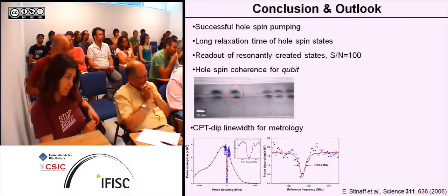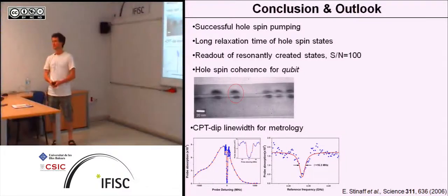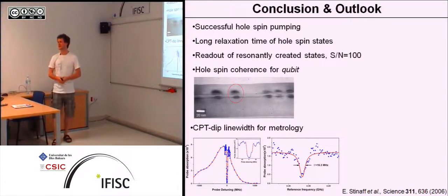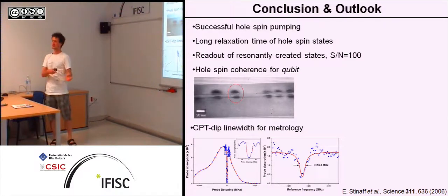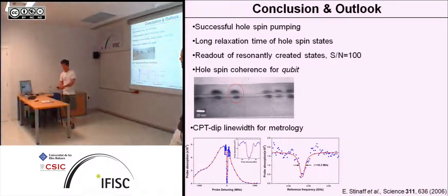Yes. So if I should be completely honest, I don't think you will ever do a quantum computer with this. No way. The different quantum dots are so dispersed in energy, it's never going to happen. But there are different schemes to create this. This is only self-assembled quantum dots, so they are subject to this somewhat random mechanism. But you can also create them lithographically. So you just grow some layer of semiconductor material, and then you apply electrodes on top of it. But because this is based on Coulomb interaction, you can only either confine electrons or holes.